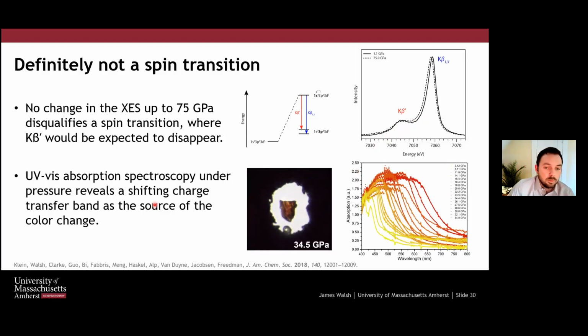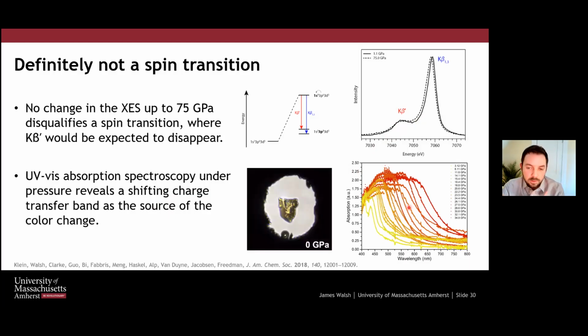And what we found with UV-vis spectroscopy is what we assign as a charge transfer band moving into the visible region, which is what's causing this color change. So not as exciting as a spin crossover, but by using techniques, we're able to actually figure out what's going on.